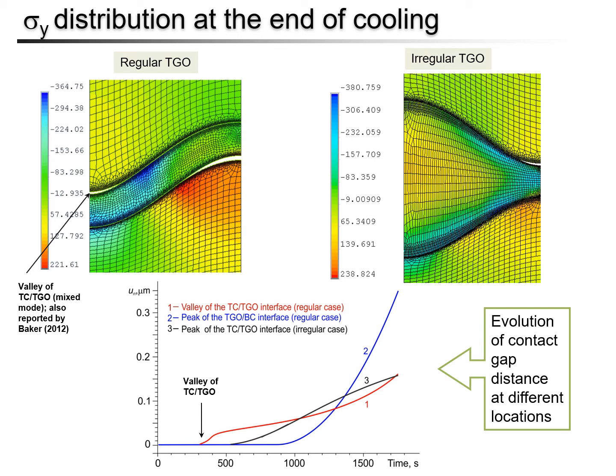Later on, about 900 seconds after the cooling starts, that corresponds to 550 degrees C, the new debonding appears at the peak of the TGO-BC interface. The interfacial cracking develops, reaching the length of 14 micrometers, but is then arrested at the asperity middle due to the presence of high compressive stresses. The Mode 1 debonding is dominant in this damage process.